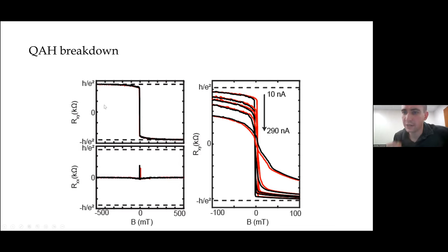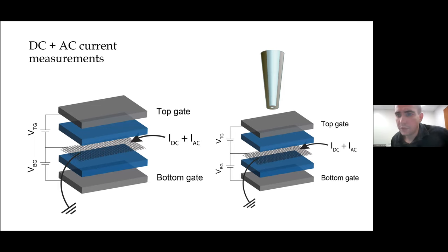In that regime, we understand electronic currents to be moving into the bulk through a variety of different mechanisms that have been proposed. In this particular system, as we go from a few tens of nanoamps up to a few hundreds of nanoamps, we see the quantization reduced to a factor of two below that expected from the von Klitzing constant. So we wanted to study this regime using both our transport data and also SQUID magnetometry. There's a couple of different contrast mechanisms I'll be showing you here. One is a differential resistance, which is measured in transport, so we're applying a DC plus AC current. The other contrast mechanism is something similar, but with the SQUID. We'll be applying a DC plus AC current and measuring the local magnetic field at that frequency. If the current is coupling to magnetic order in terms of destroying it or flipping it, we'll see that locally with the SQUID.